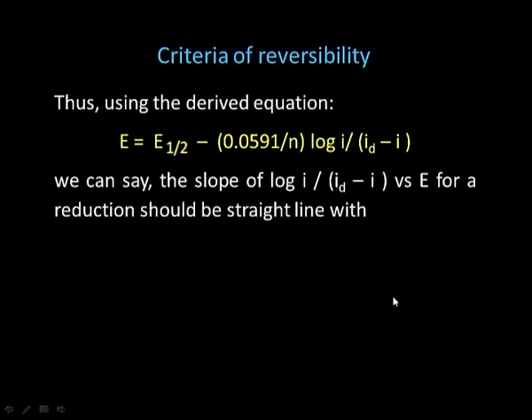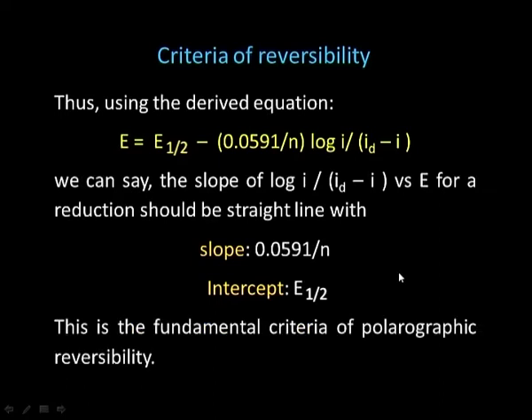Thus, using the derived equation, we can say the plot of log I over ID minus I versus E for a reduction should be a straight line with the slope 0.0591 divided by n. The intercept of this straight line should be E half, and this is the fundamental criterion of polarographic reversibility. There are many techniques which have been derived from polarography and are more sensitive in comparison to normal polarography. The first one is pulse polarography.